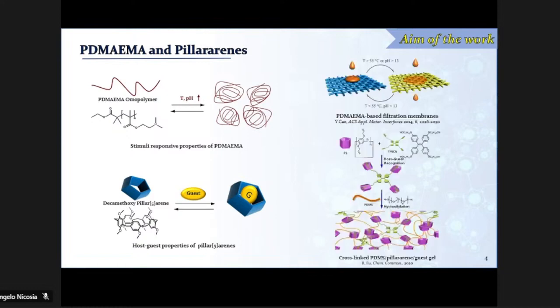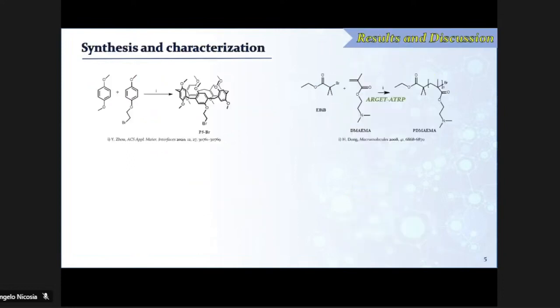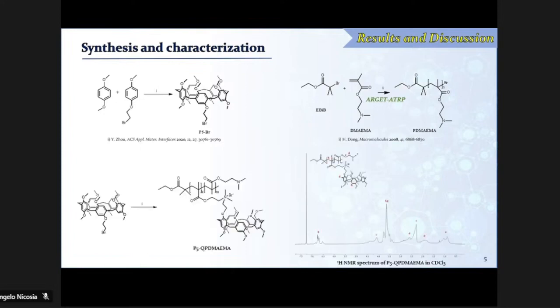These polymers already find applications for the preparation of cross-linked polymers or blended polymers for environmental remediation applications. So we synthesized a pillararene derivative with a bromoethoxy functionality and PDMAEMA by an ATRP polymerization, and by a simple quaternization of the dimethylamino groups of PDMAEMA with the pillararenes, we were able to obtain a new smart polymer that we named P5Q-PDMAEMA, fully characterized by NMR spectroscopy. Here I show just the proton NMR spectrum, in which it is possible to observe the proton signals related to aromatic functionalities of the pillararenes.